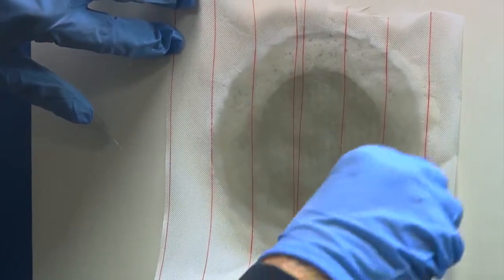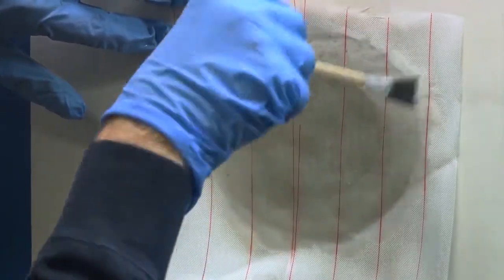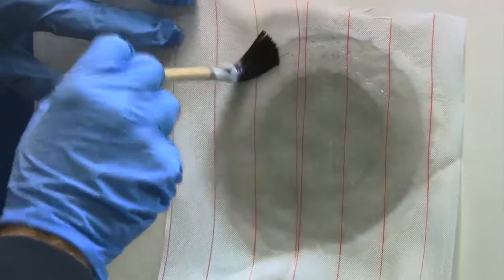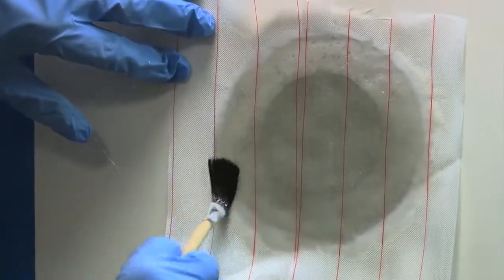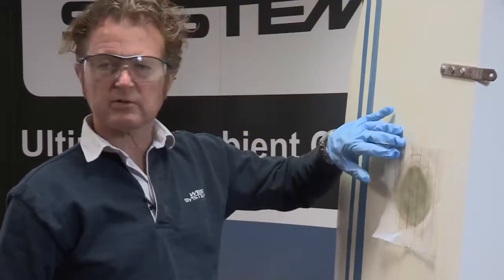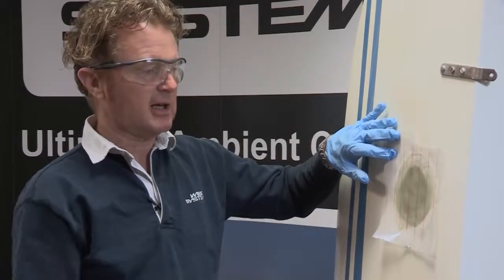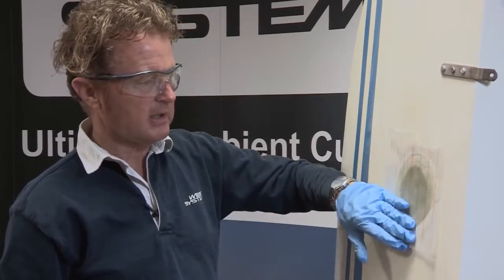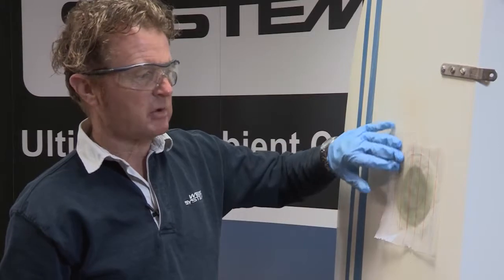Peel ply really does protect the laminate from any damp that might occur during the night, because now we're going to leave this for a full 24 hours to cure before we rip the peel ply away and then see how much work we've got left to do to finish this off.